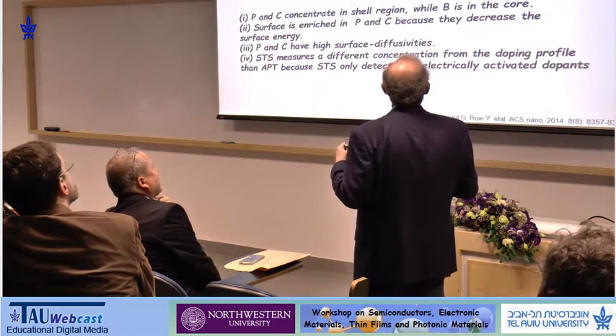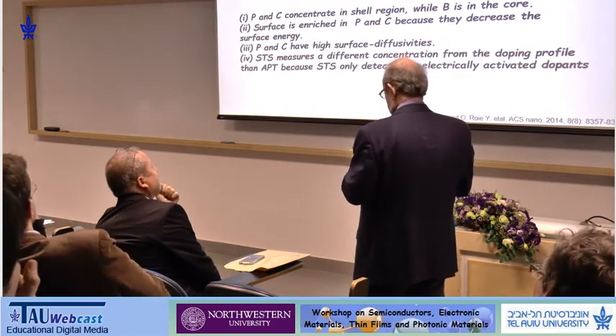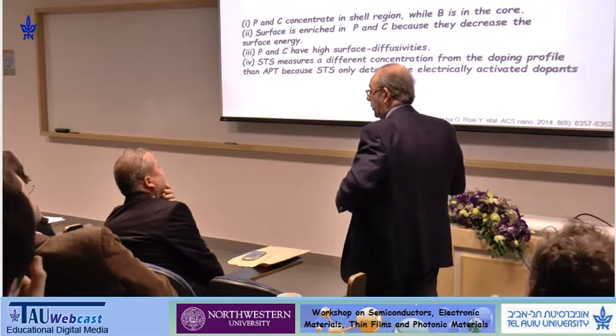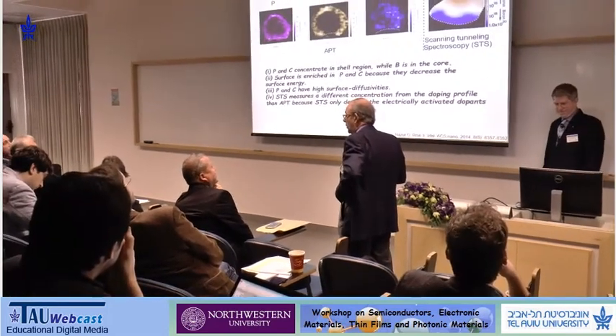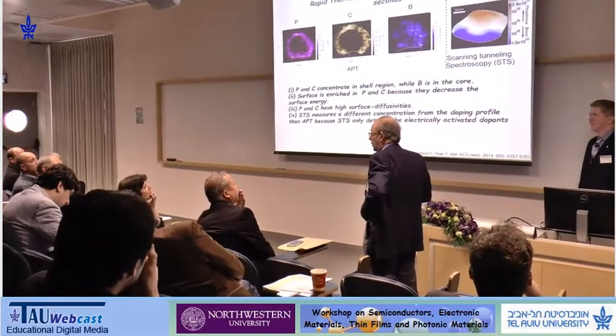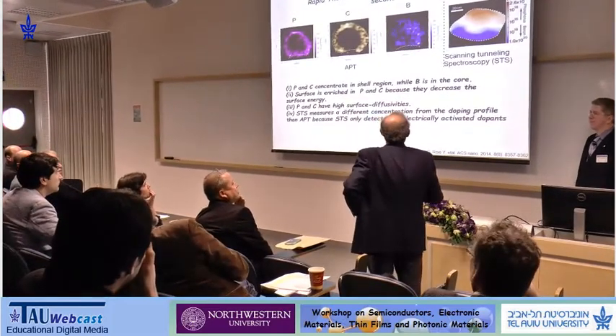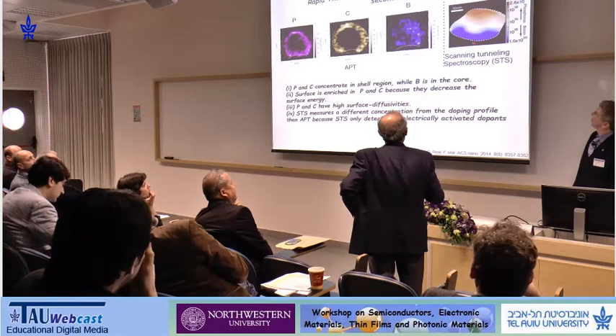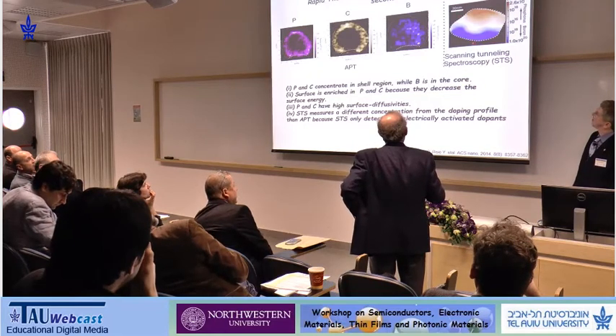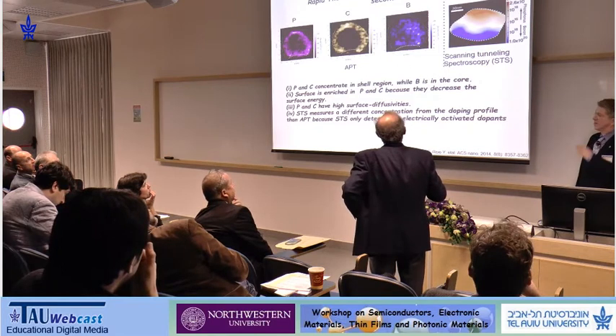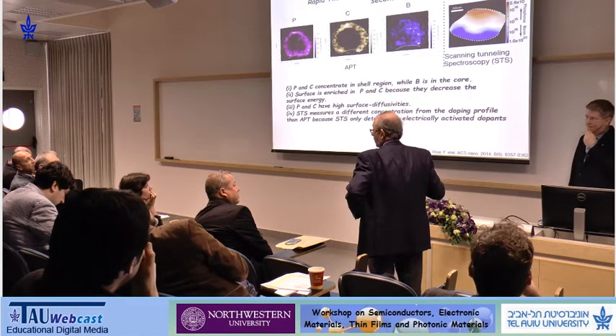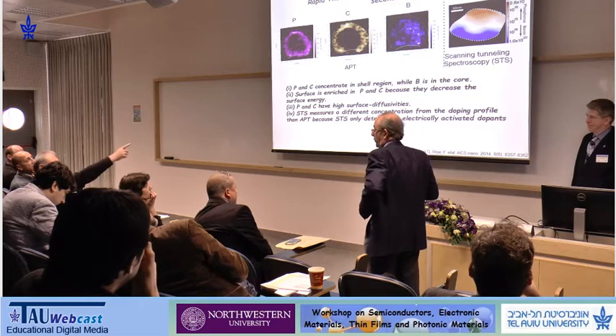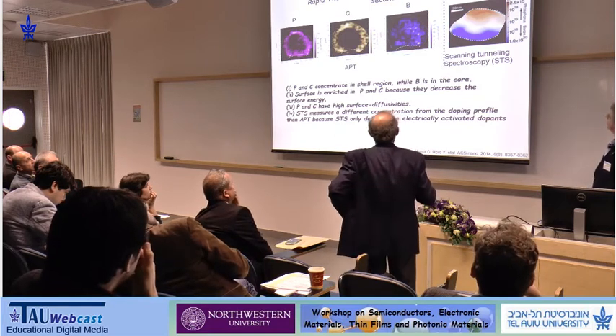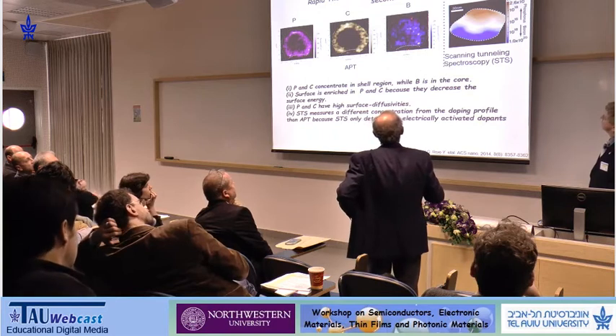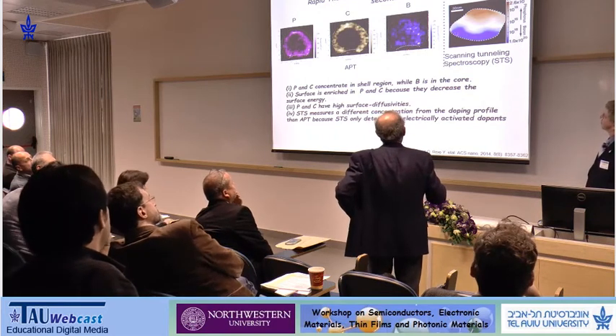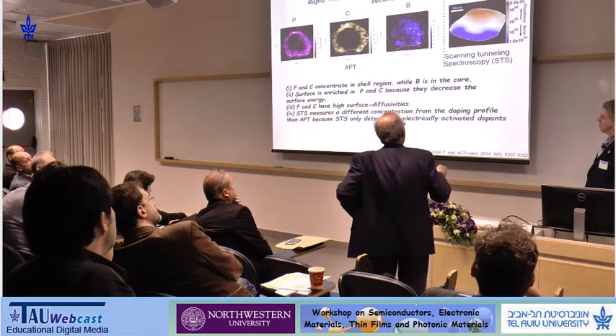Yeah. So I understand the atom probe part. I'm not sure I understand how the bias-dependent STM was taken here. Is it the same sample, a different sample? This is a different sample. This data was supplied by Roy E., but he uses the same prescription here, 970 degrees C for 20 seconds. But what are we seeing here? You're seeing the distributions. Just like here, you're seeing the distribution of boron, which is uniform. And here you're seeing the boron, and here the phosphorus.